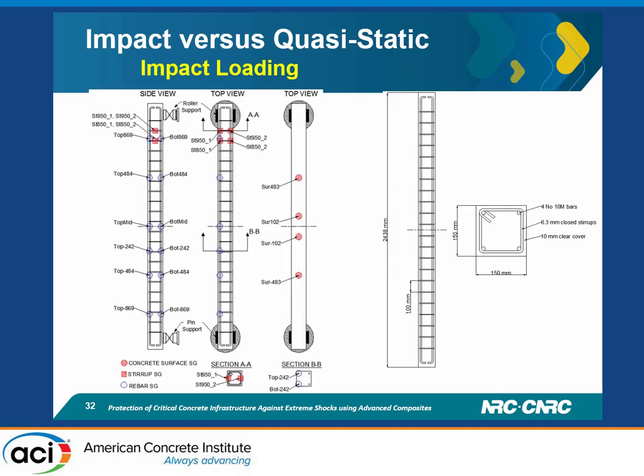So, in the impact test, we did exactly the same boundary. We also have lateral pin rollers, and we apply axial load at the same level, but then we apply impact force at the mid-height of the column using a special device where we pre-accelerate a mass, and then a hard surface impacts the mid-height of the column. We changed the distribution of the strain gauges inside to maintain good monitoring of the strain wave as it migrates through the column, and we monitor the reactions, the axial load, and also the cracks using a high-speed camera.